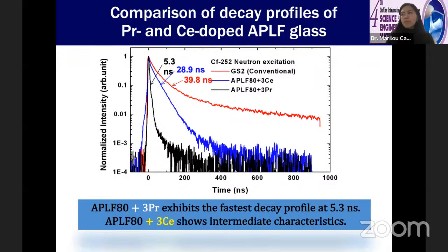So we characterized the performance of our APLF glass scintillators. In terms of performance, we compared the luminescence decay time with the conventional GS2 scintillator. For this purpose, we used a californium 252 neutron source as excitation. We can see that for the conventional GS2, the decay time is very long, 39.8 nanoseconds. But also there is this afterglow that is disadvantageous when using a material as a scintillator, because we want a sharp response time for our scintillator.